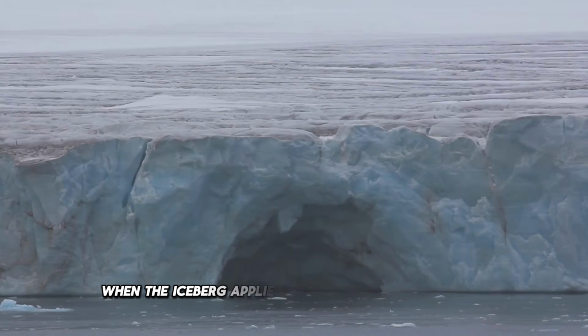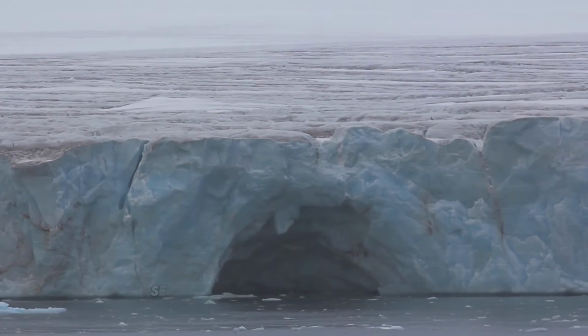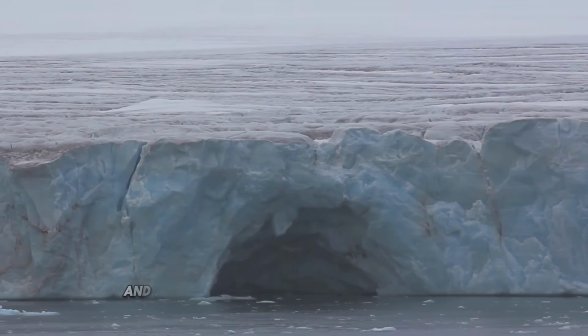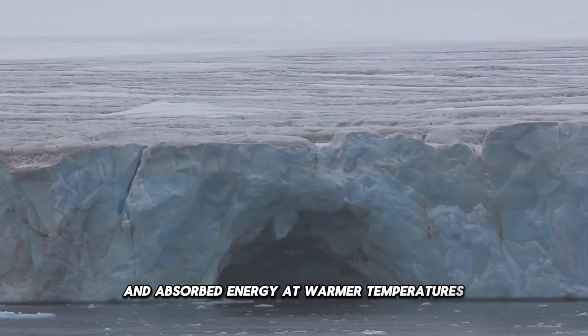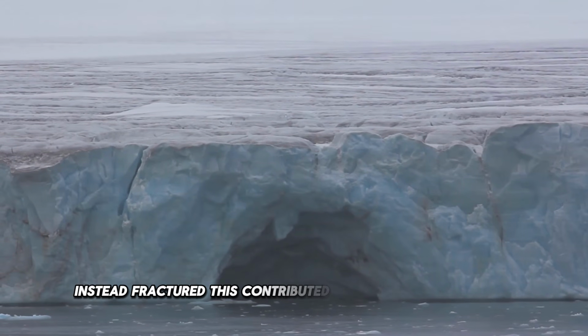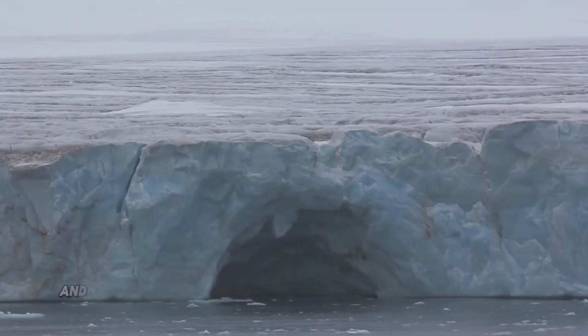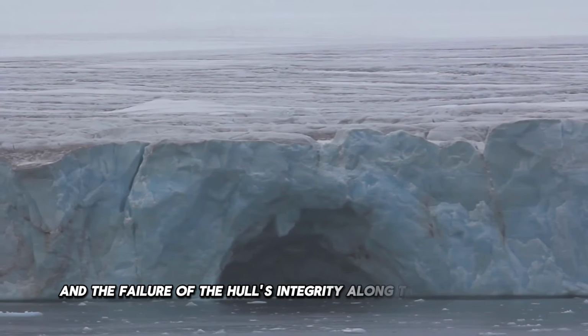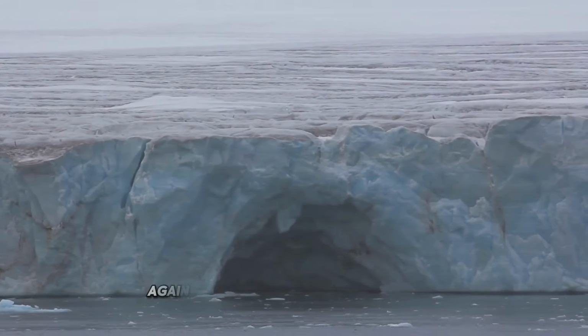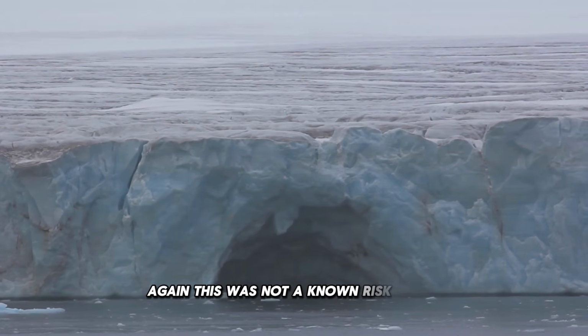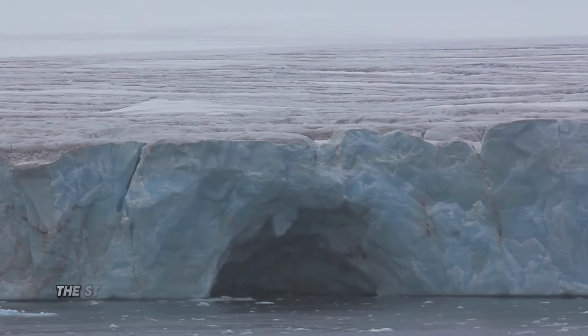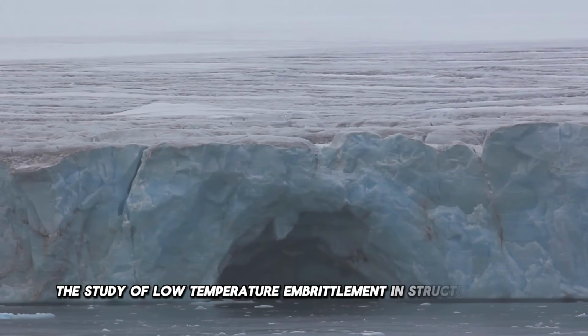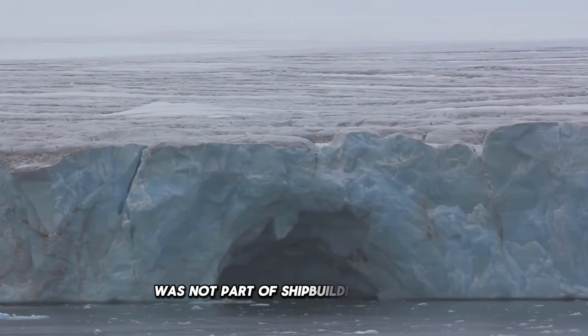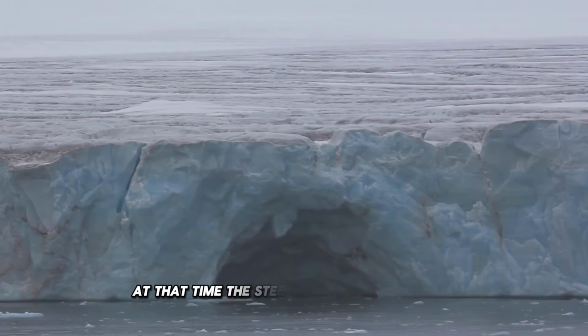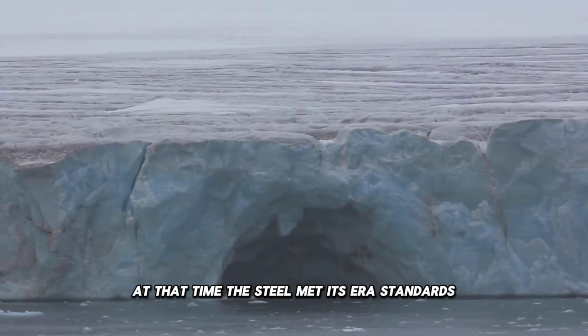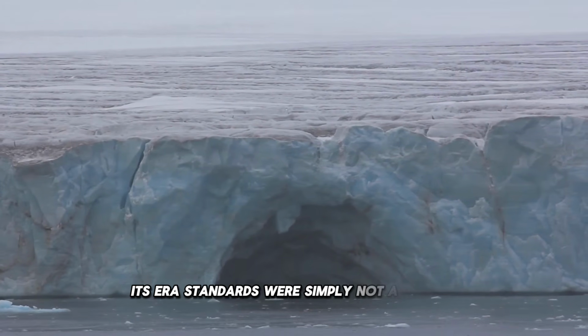When the iceberg applied impact loading to the hull, sections of steel that might have bent and absorbed energy at warmer temperatures instead fractured. This contributed to the opening of seams and the failure of the hull's integrity along the contact zone. Again, this was not a known risk in 1912. The study of low-temperature embrittlement in structural steel was not part of shipbuilding practice at that time. The steel met its era's standards. Its era's standards were simply not adequate.